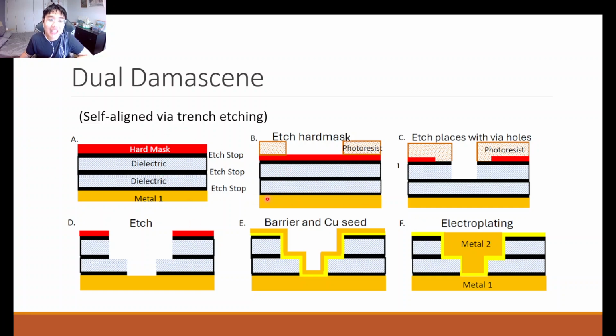An example of a self-aligned via trench etching is shown here, where you first have a hard mask, you etch your hard mask, then you put a photoresist, and then you etch down a certain amount. The width of this first dielectric etching is the width of your via, and then your second etch means that your second dielectric will now be etched downwards with the dimension of your via. But now, your first dielectric layer is etched based on the dimension of the hard mask, which is the dimension of the trench. So in the second etch step, we open up both the via and the trench simultaneously, and these two are aligned by this single etching step. So we call this a self-aligned via and trench etching.